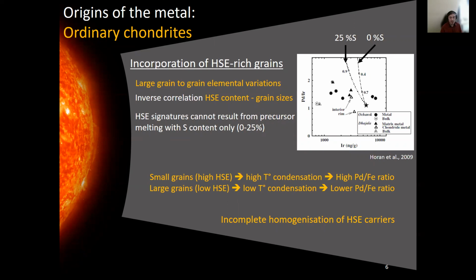However, in the case of ordinary chondrite, condensation and silicate reduction cannot explain the elemental composition of the metal. The formation of metal phase in ordinary chondrite is therefore subject to debate, and two main hypotheses exist. The first one suggests that highly siderophile elements rich grains have been incorporated within the metal during metal formation.